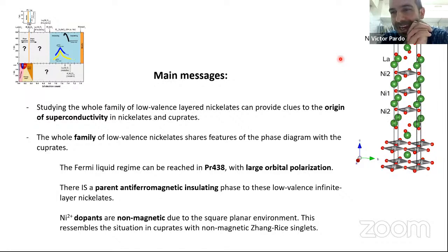No, I don't know why STO would be important. I don't see it. Apart from sample questions, that you need to grow them in a particular way, with a substrate, I don't see any electronic structure role of the STO. I don't see any magic like that happening, as in the iron selenium, for example, that only grown on top of STO you get something which is really unusual. But only for monolayer. But then, right.